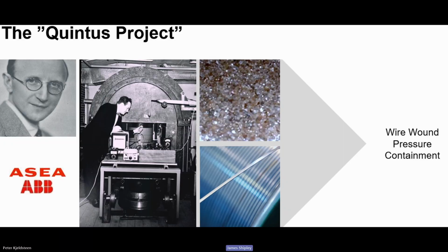Our specific design is based on technology that was developed during the Quintus project, actually at Asea in the 50s for the diamonds, which is wire winding of forgings. So we actually take forgings that we have sub-suppliers for, that we then wind with a metal wire, or spring steel, you could say, which is putting compressive stresses into the forgings. And the amount of wire winding, the amount of pressure, etc., in order to put compressive stresses into the forgings, depends on the size of the machine and also the pressure rating. Basically, we're creating a forging that's under immense pressure itself, so that when we put gas inside and we pump the pressure up, the wire is kind of forced out again, but never past the design point.